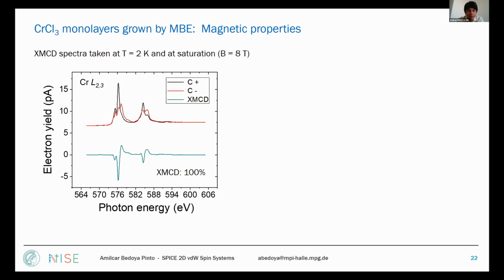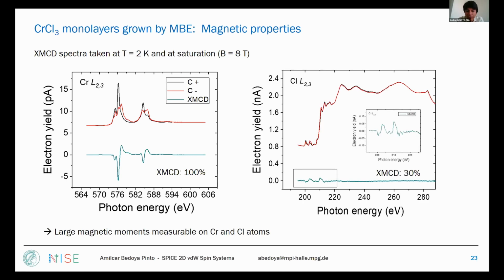So going to the results. We have here the XMCD spectra taken at 2 Kelvin at the saturation fields. And we see here at the chromium L edge a very large XMCD signal of around 100%. So that actually also underlines the quality of our chromium chloride monolayer. And we can even see that we have a sizable XMCD signal at the chlorine L edge, at low photon energies. So that means that at 2 Kelvin at saturation, when we expect that all the spins are saturated, we have a large magnetic moment.